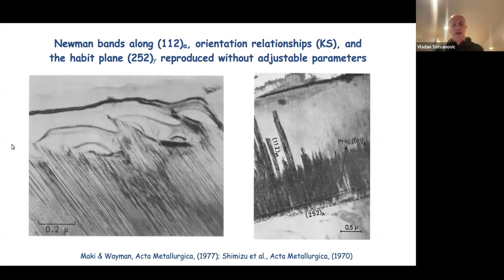And if you ask what the direction of these twin boundaries is, you find 1, 1, 2 in the BCC basis, which is exactly the slip that we found. You find it in this other picture as well. What I haven't told you about, but you can read in our paper from a couple of years ago, is that our mechanism also produces the most often experimentally observed orientation relationships between the two phases, which are called Kurdjumov-Sachs, or KS, orientation relationships, and also the habit plane between these two crystal structures, the coexistence plane, which is 252, which you can also see in this picture.